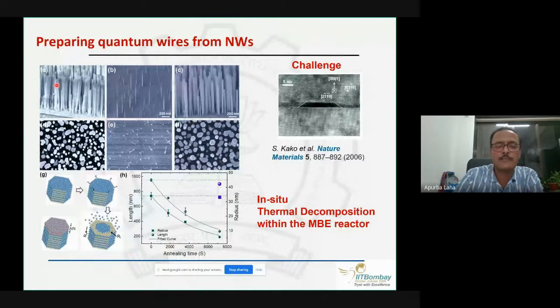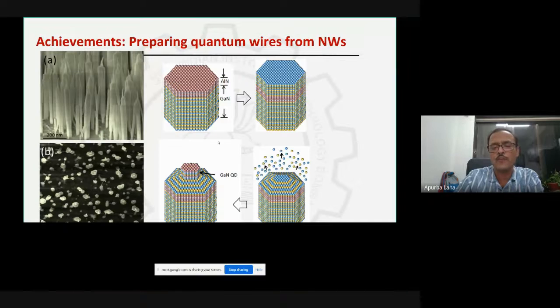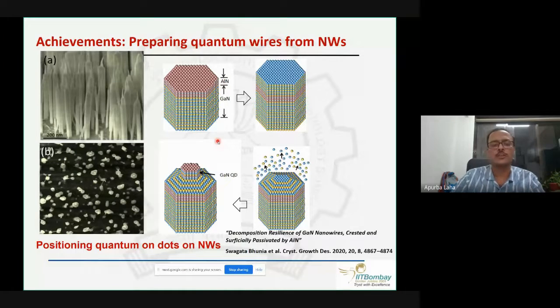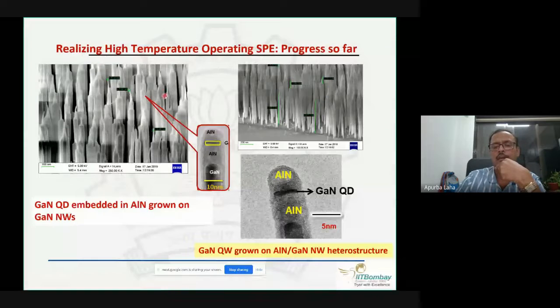You will see here in the structure, these are the gallium nitride nanowires, and we convert this gallium nitride nanowire into the quantum wire, and these quantum wires are the template for holding the structure. For example, here in the tiny tip you see, this is where our quantum dots are placed. And in high resolution transmission electron microscopy, here you see the gallium nitride quantum dot placed on the nanowire, a gallium nitride template.